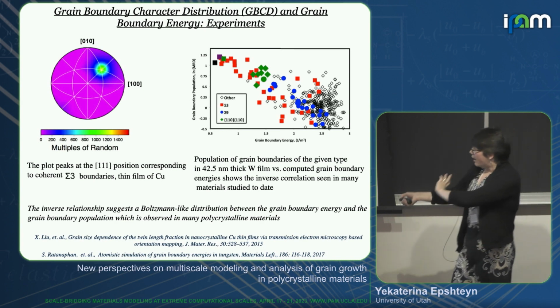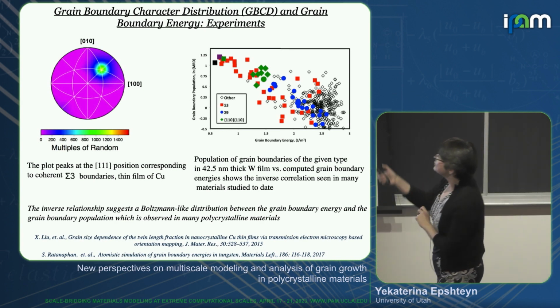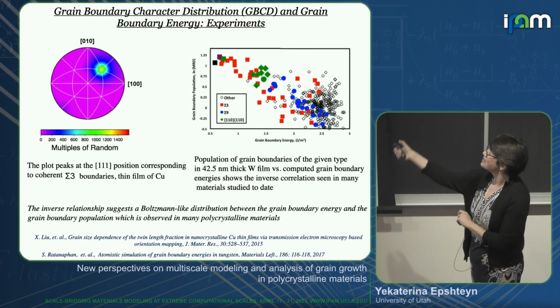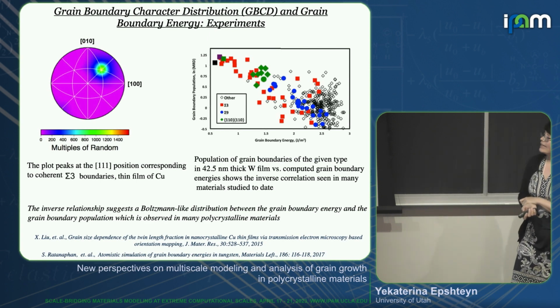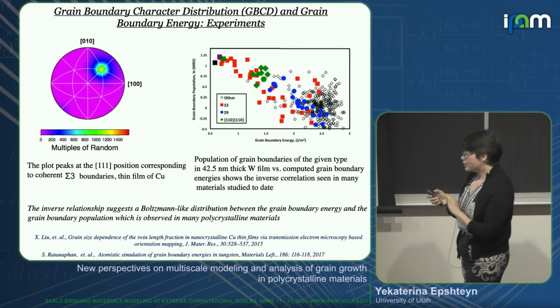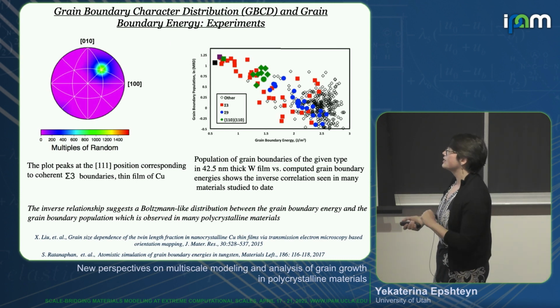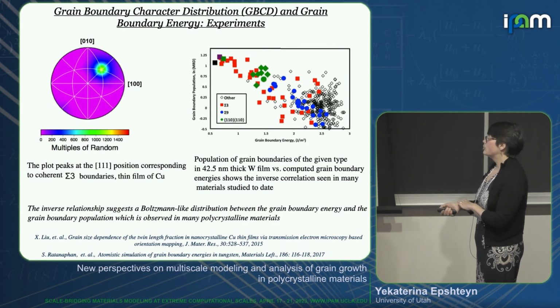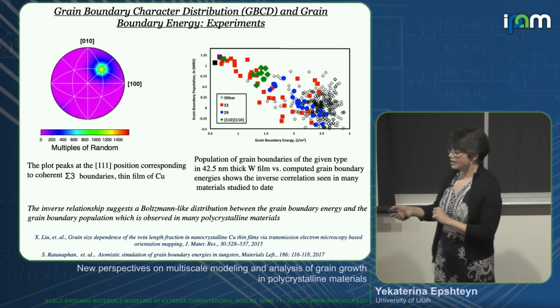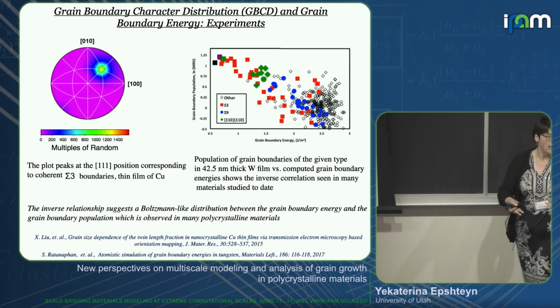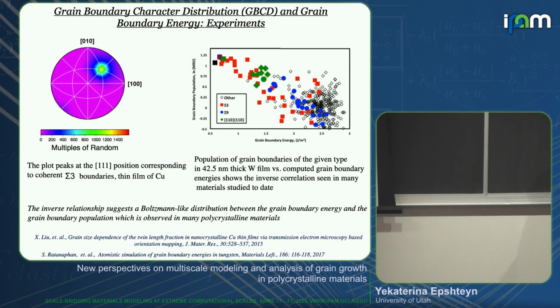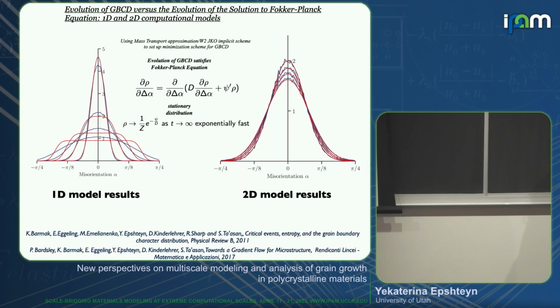And here are experimental results. You can see sigma 3, sigma 9, that are also consistent and basically show the inverse relations, a Boltzmann-like distribution between grain boundary energy and grain boundary population. So experimental results also indicate a similar relationship between grain boundary energy and grain boundary population.